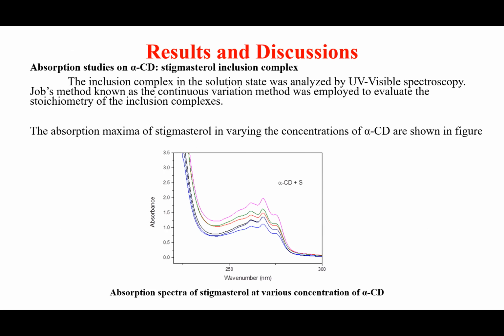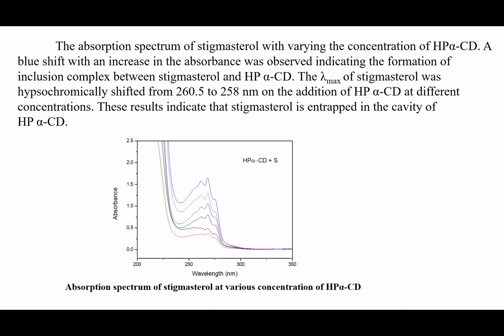So here, coming to the results, we have taken absorption studies varying the concentration of alpha CD. This is the UV plot obtained. So here the wavelength is varied as the concentration of alpha CD varies. Stigmasterol concentration is kept constant. This is for HP alpha CD. So here the lambda max value is shifted from 260 to 258 nanometer on addition of hydroxypropyl alpha CD. This indicates the stigmasterol is entrapped in the cavity of HP alpha CD.